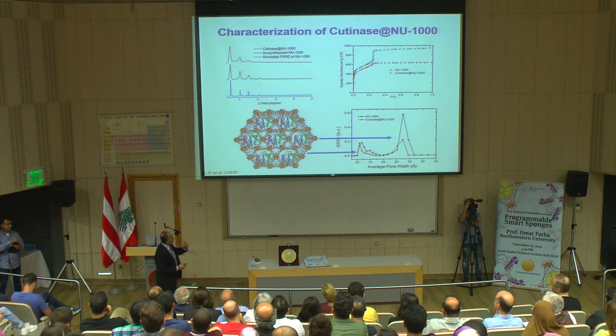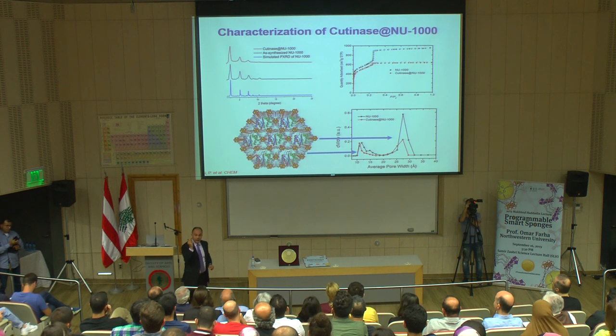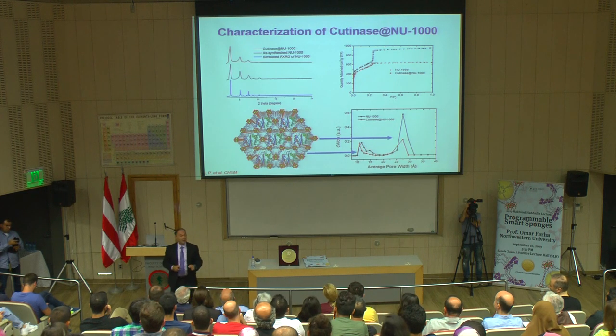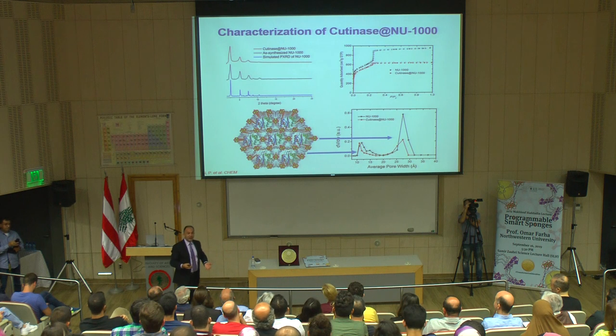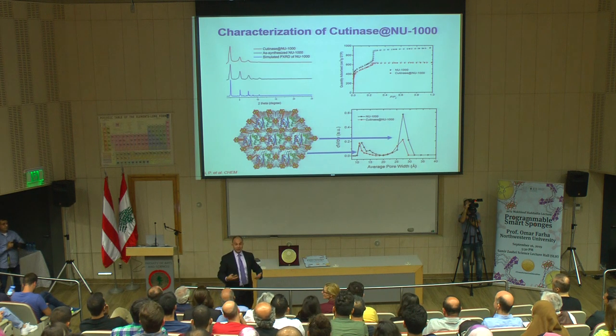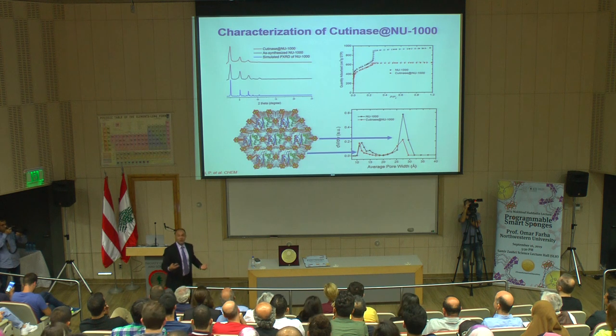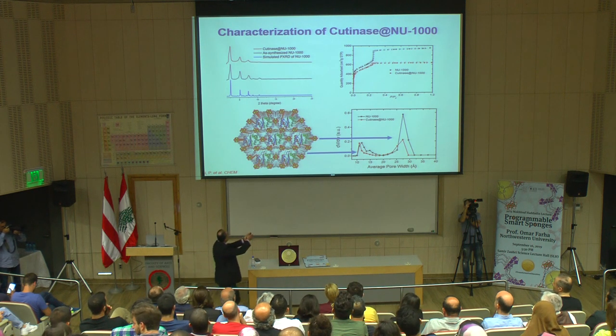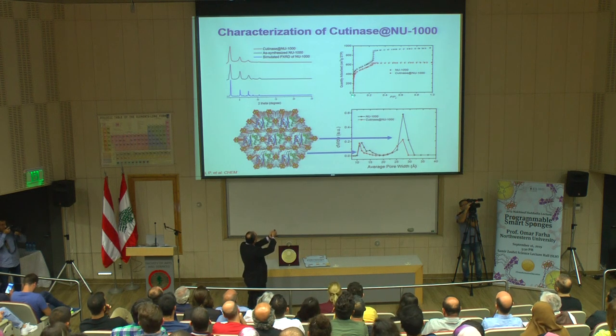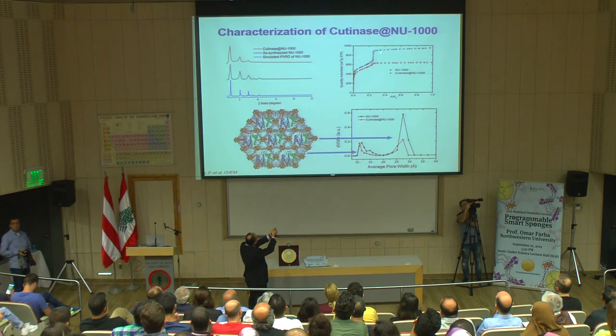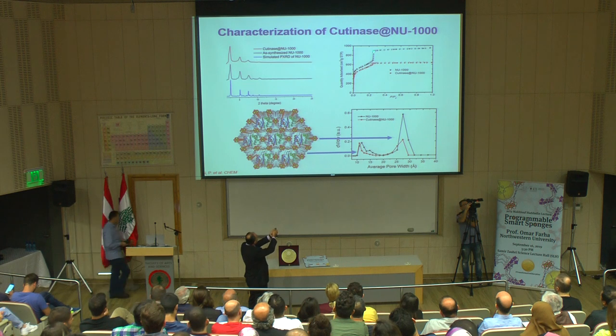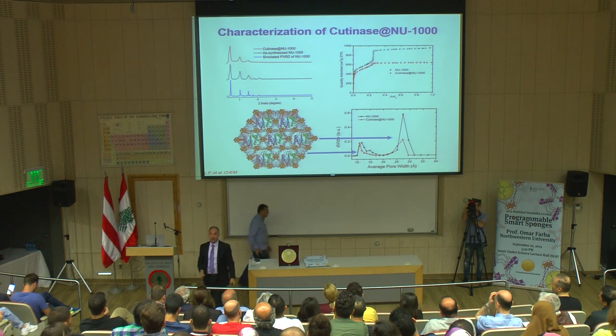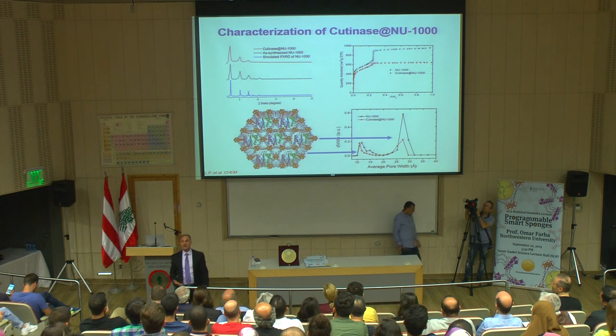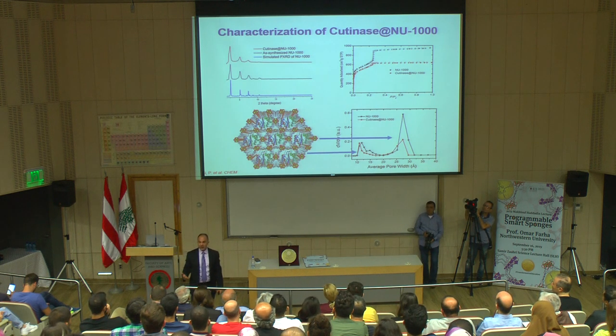We characterize this material, and we know that we made the right thing. That's the PXRD. But more importantly, how do we know that it went into the hexagon but not the triangle? So what do we do here? Some people sitting in the audience use this technique all the time as well: taking a nitrogen isotherm. What do I mean by that? At 77 K, you measure the uptake of nitrogen with pressure. You see here, that's NU-1000, the MOF I showed you before we put the enzyme. This step here is a signature of the 3.2 nanometer channel. If it wasn't there, that means we don't have that mesoporous channel. Trust me for that, and we'll revisit this in a few slides.